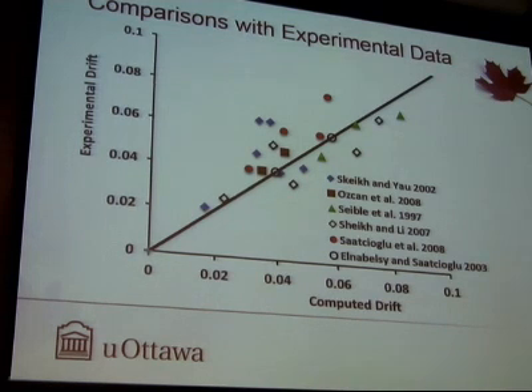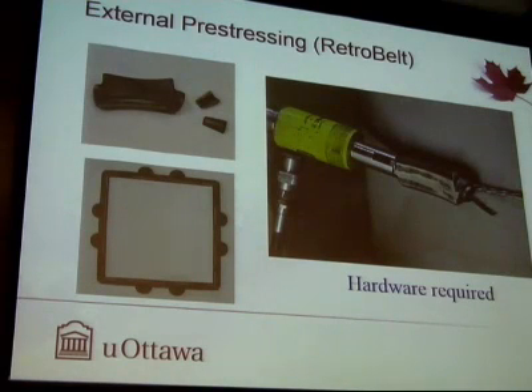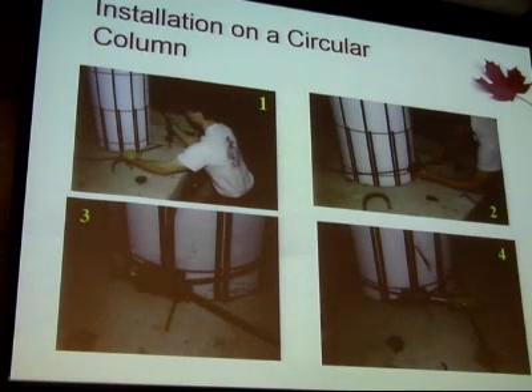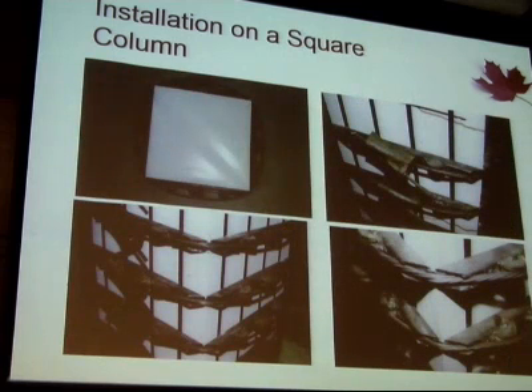There's fairly decent agreement. Now, the second technique that I would like to talk about is transverse pre-stressing of columns for enhanced strength and/or deformability. As we all know, pre-stressing is not done in the transverse direction, but this application is intended to introduce active pressure over and above the passive pressure that we introduce through existing transverse reinforcement. And the technique can be implemented in either one of two ways. Firstly, we can use 7-wire strands and wrap the strands around the columns with ring anchors and pre-stress them to induce lateral transverse pressure.